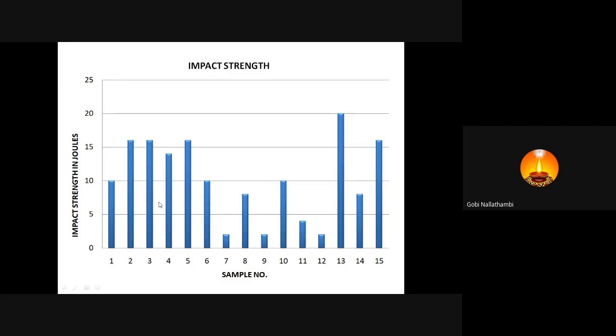So if you see the result for the same composite, sample number 13 gives the highest impact strength compared to all other samples. 14 and 15 also give moderate values, but 13 shows a very low value with respect to tensile strength. But here 13 shows very high impact strength. We will discuss why that happened.